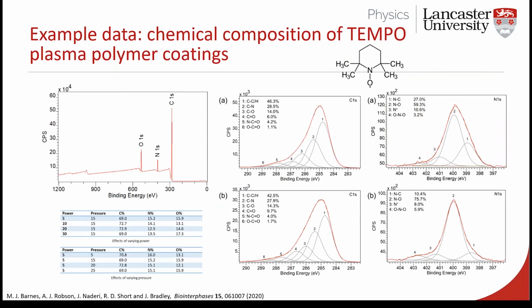So this is the sort of information we get out of that. We put in a sample, this one up here. So this was created by a plasma coating. We do our wide spectrum scan. So this is our survey scan. We see very quickly that predominantly this is made of carbon, nitrogen, and oxygen. So at first point, that makes a lot of sense. We zoom in on these peaks and we do high resolution mapping, and we can pull out very clearly all of these different carbon species, for example, nitrogen species. And it gives us real chemical information about a real surface.